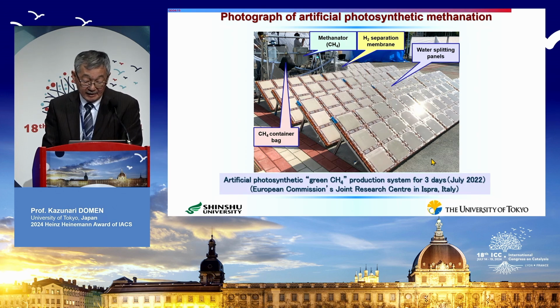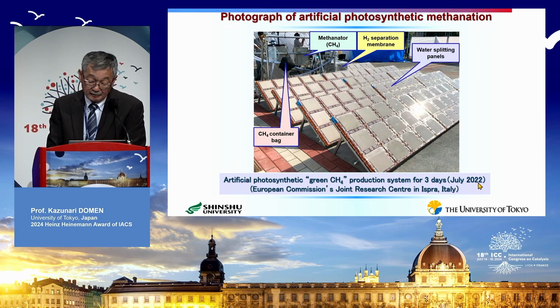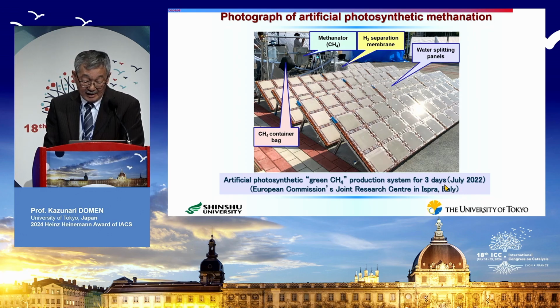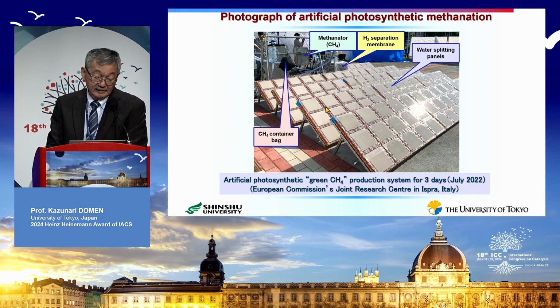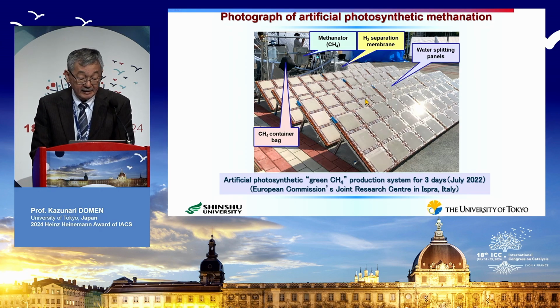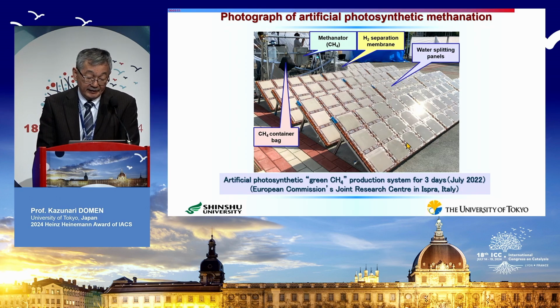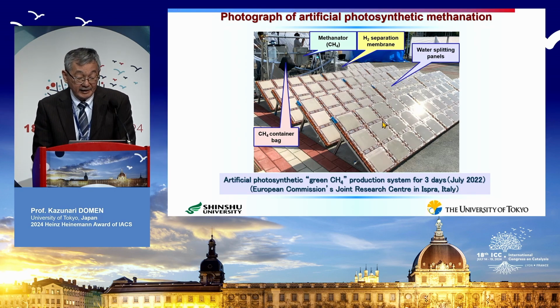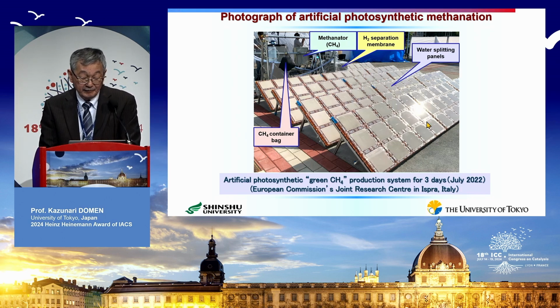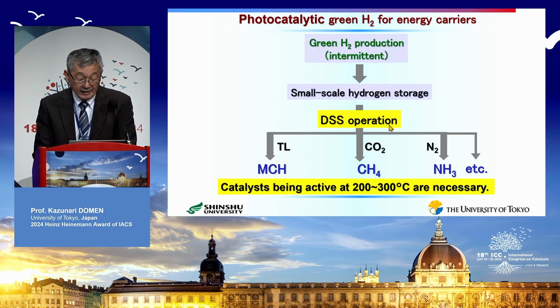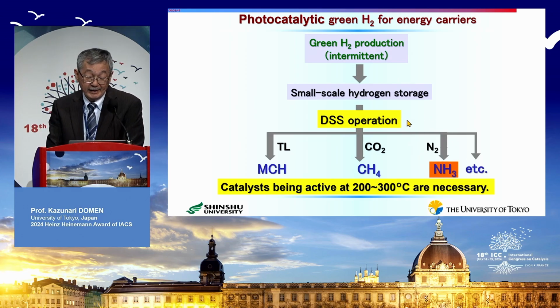And actually, we carried out this kind of experiment in July 2022 at the European Commission's Joint Research Centre in Ispra, Italy. We carried out a 3-day DSS operation, all computer controlled. And this system worked well. From this experiment, we are rather confident that it is not so difficult to extend this type of system to a wide area, as long as we can develop a highly efficient water splitting panel. And at the last part, let me discuss ammonia formation by this method.